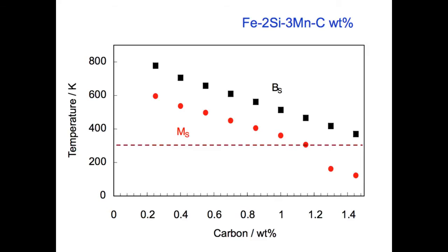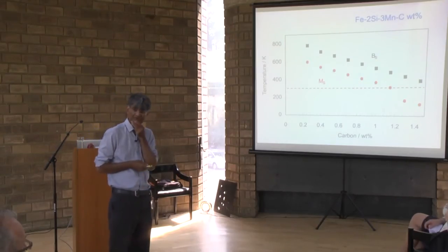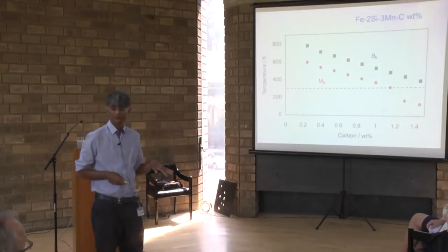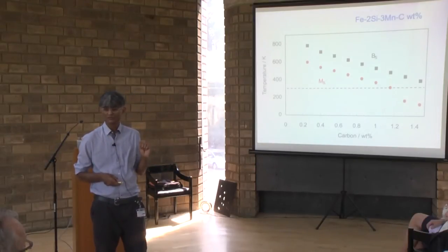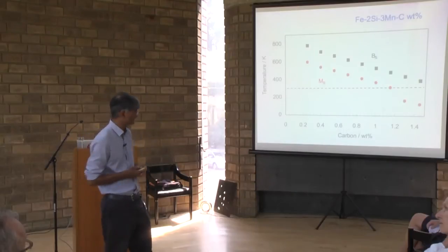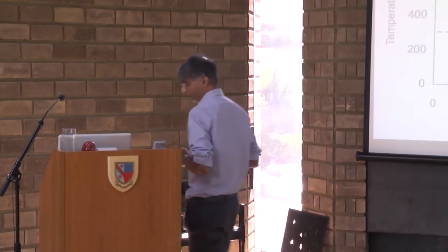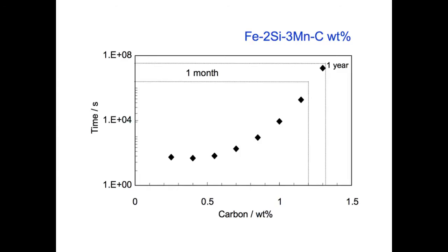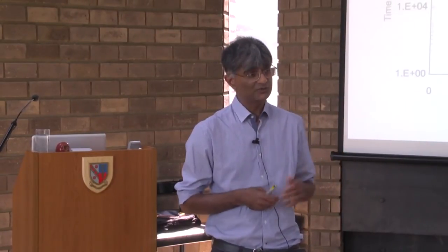So what we want is a steel where a gap is maintained between the good stuff and the bad stuff. And what we discovered from theory is that there is no limit to the lower temperature. We could go down to room temperature and form these crystals, let them grow inside the steel. But the problem is, if I actually form the crystals at room temperature, it will take me about 100 years. Yeah? So that's like wine. You make the steel, you store it, and then you sell it in 100 years. But I couldn't convince any of the industrial partners to take that up.